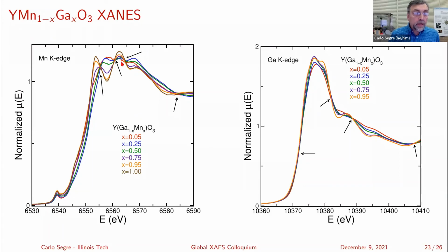We have not completed any EXAFS analysis on this. We're concerned because of the garnet phase. We really would rather have a much more pure phase to get this done. But it's promising, it's interesting. And now the question is, well, is there a way that I can work on this without having to make the full composition range? Because the other materials have a limited composition range, the other colors.